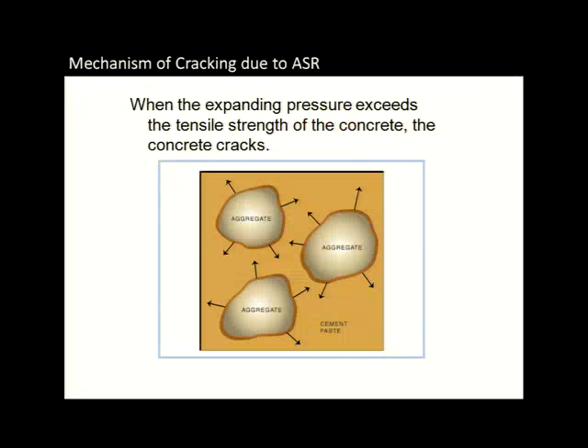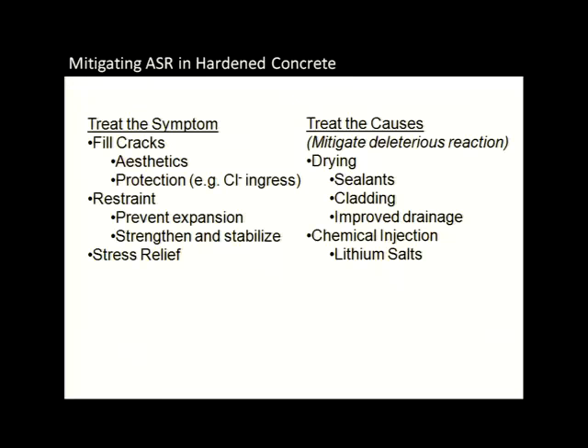This just kind of shows you the idea of what's happening. You've got aggregate inside a cement paste, and this can happen to both fine and coarse aggregate in the Portland cement concrete. And as that gel around the aggregate and inside the aggregate expands, it can actually crack the concrete apart. When you crack the concrete apart, you're opening up a fast path for other aggressive agents to come in. An aggressive agent may be water, just water coming in to help drive the expansion in the reaction more. You also set up the propensity for increased corrosion, freeze-thaw attack, and sulfate attack. So certainly we want to do everything we can to limit cracking in concrete.